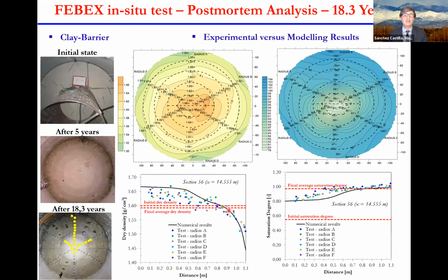These are the final results after 18 years of hydration. So this is the barrier at the beginning of the experiment, after 5 years, and after 18.3 years. These are experimental results obtained from the post-mortem analysis from this test. And this is the distribution of densities and saturation. You can see that it's more or less uniform. This implies that the barrier was more or less uniformly hydrated from the boundary.